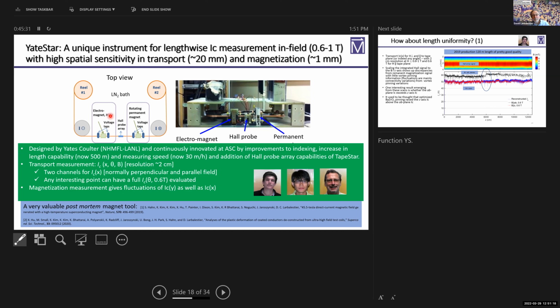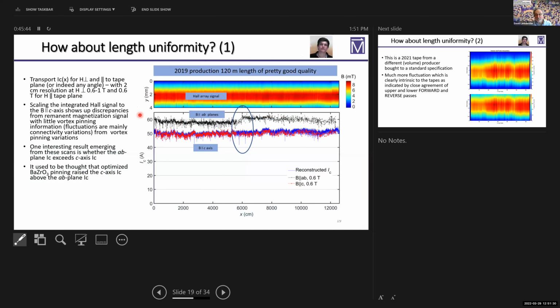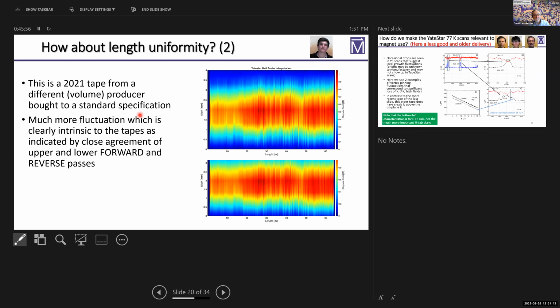And so we have a device where H can be parallel to the C axis or typically parallel to the AB plane, but we actually use a rotating permanent magnet. So it's quite versatile. And when you do things like this, you see that the critical current density can be pretty good, but it's not perfect. But this is definitely pretty good, and I think would be quite acceptable.